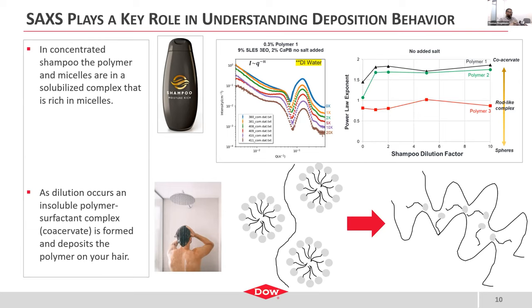So what you do in this sort of a formulation is in the concentrated shampoo, which is the shampoo that you have in the bottle, the polymer and micelles are solubilized in a complex. And what I mean by that is similar to what's shown in the center here at the bottom, where you have your deposition polymer that is surrounded by spherical micelles that keep it in solution during the shelf life, in its concentrated state. Now, you put that in your hair, you get it all foamed up and lathered up, you get under the water and you undergo a dilution event.